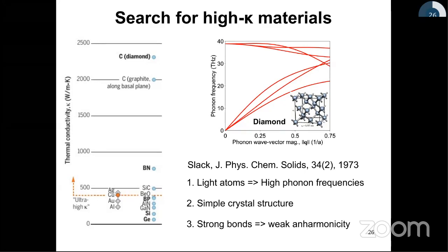So Glen Slack in 1973 actually looked at all of these high thermal conductivity materials, that is materials which have thermal conductivity more than say 300 to 400. And he found several common features among these materials which give them the high thermal conductivity. For example, if you look at the list on your left, all of these materials have very light constituent atoms. We all know that when you have light atoms, you have high vibrational frequencies and high group velocities. He also noticed that these materials have very simple crystal structures and very strong bonds, which means their anharmonicity, which drives phonon-phonon scattering, is also very weak.